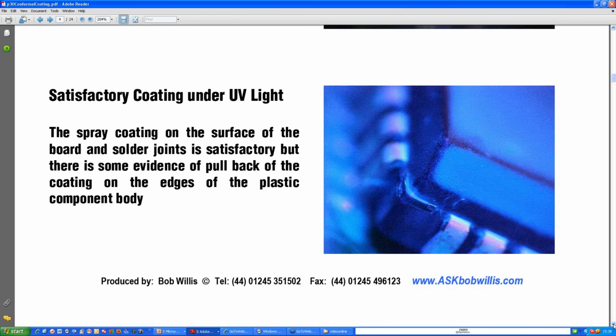Now, in this illustration, this photograph, I show a PLCC again, a plastic leaded chip carrier, but you can see here that the coating does not appear to be present on the edges of the plastic. Now, this is a common thing which happens in conformal coating. On some plastic components, you can get poor coverage or even de-wetting on the surface due to the mold release compounds that are in the plastic packages as part of the fabrication process of the components.